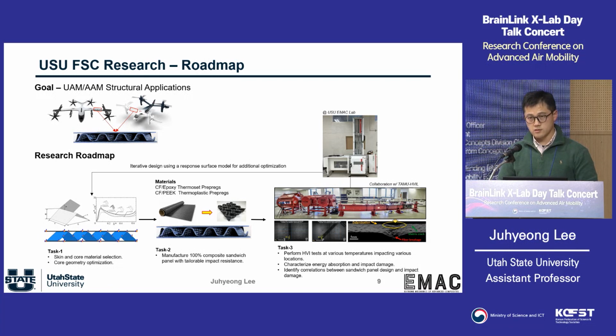So we use the traditional composite manufacturing process, but recently we started to make the same structural panel using 3D printing. Not only extrusion-based 3D printing, we're also looking at lamination-based 3D printing, because the traditional manufacturing process takes at least 1 day just to make small pieces. But if you apply additive manufacturing for the composite, for polymer, we can directly print the same architecture in an hour. So 1 full day versus 1 hour, that's a huge difference in terms of mass production.